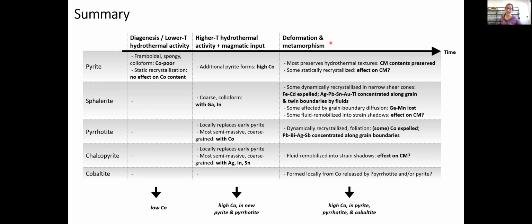If we look at what's happening in each stage, early diagenesis, well, the only sulfide we really have around at that time is pyrite, and that's the only one that preserves textures. And at that point, we're forming the pyrite 1A, colloform framboidal pyrite, cobalt poor, overall very little cobalt in the system. Then we have the main mineralizing stage. We've added these hot hydrothermal fluids with a whole lot of metals. We form high cobalt pyrite. So we've added additional pyrite with a lot of cobalt. And we go and form a bunch of other sulfides, carrying various other critical metals.